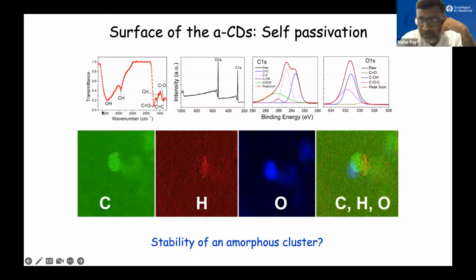X-ray photoelectron spectroscopy, photoemission spectroscopy. And these are the elemental mapping, which clearly shows we have a central region of carbon surrounded essentially by hydrogen and oxygen, which are not very homogeneously distributed, but somehow encapsulating that cluster of carbon atoms.